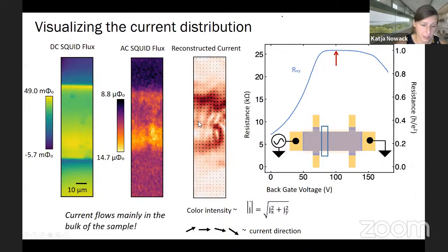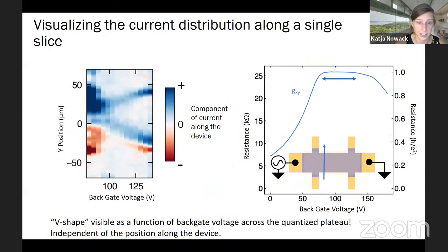And what is really surprising is that when we went into this, we were expecting to see the current strongly confined along the edges, because we were expecting that the transport current that we apply is carried predominantly by the edge modes of the quantum anomalous Hall insulator. And we find that this is not the case.